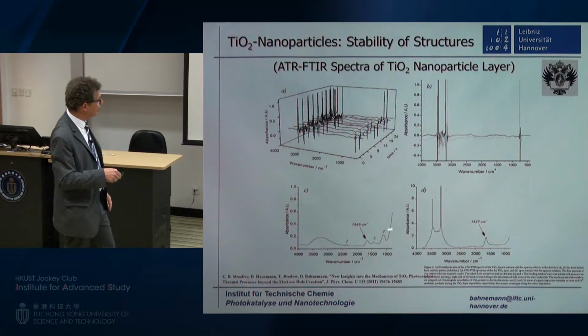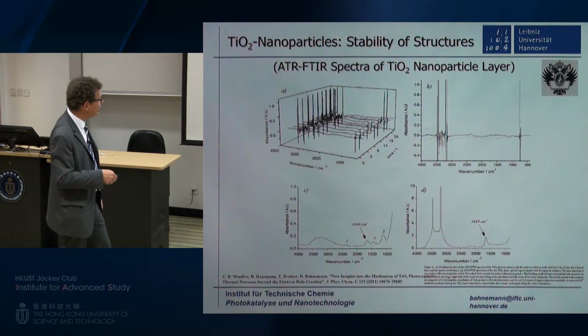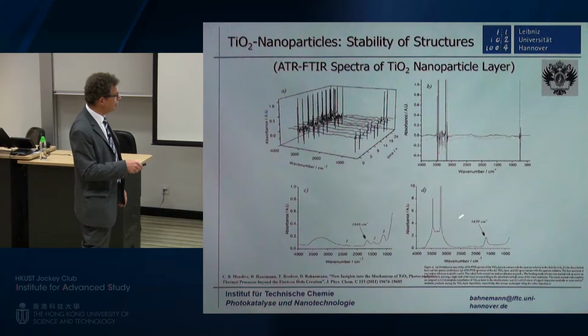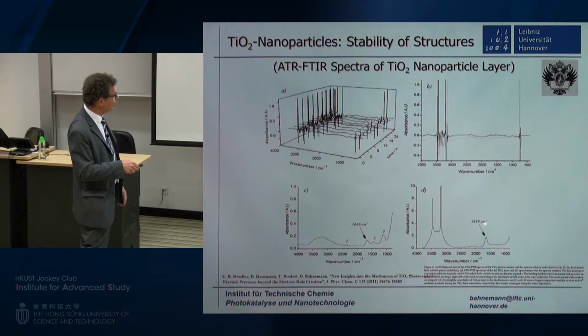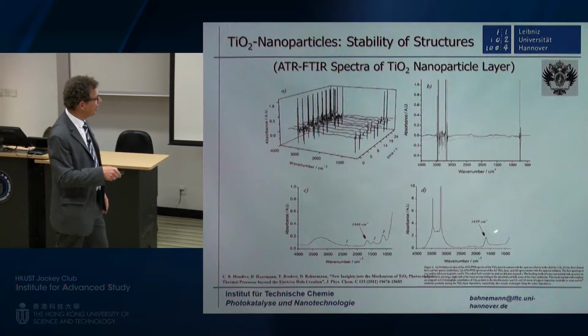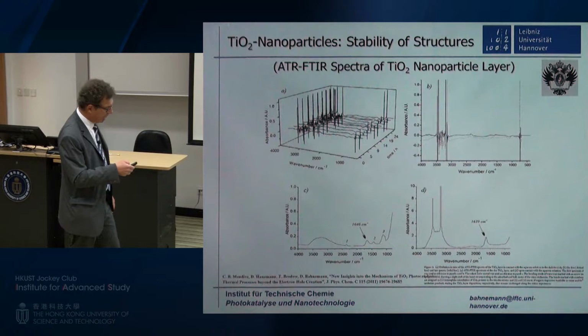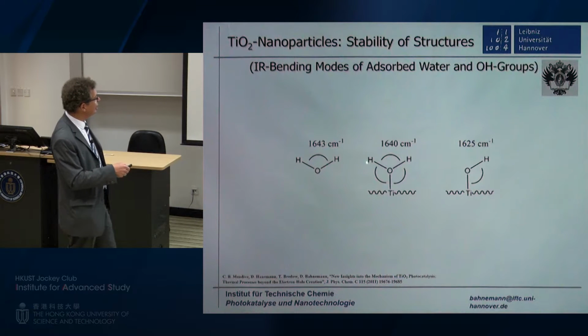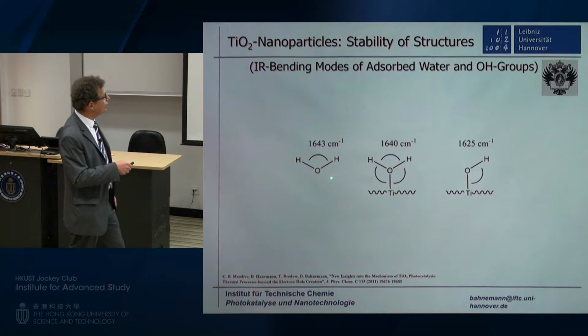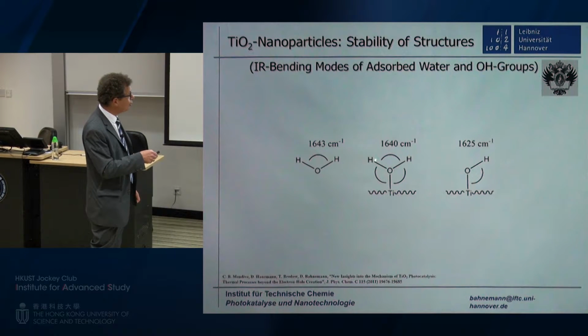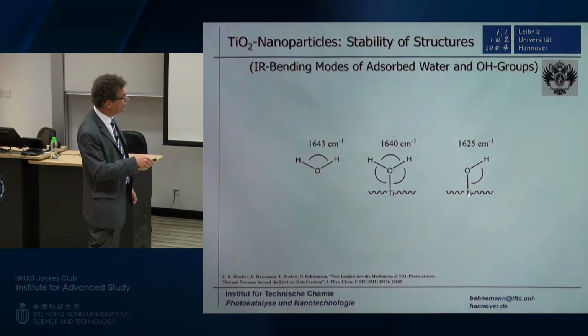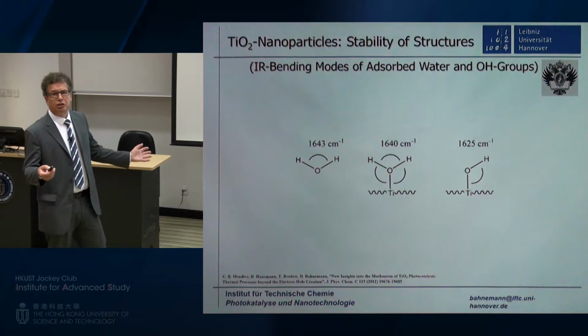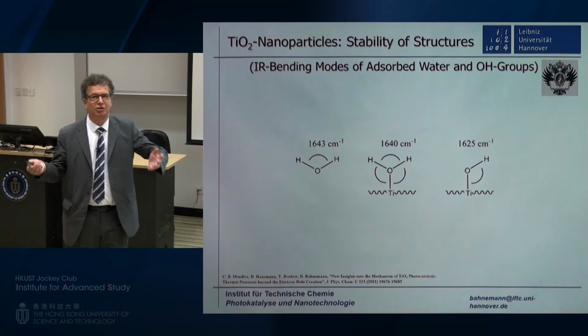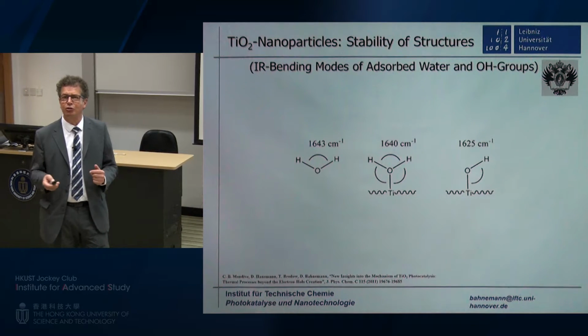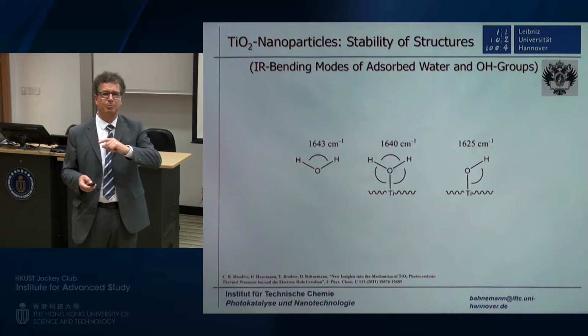You get certain bands here, and the interesting bands are around 1640 wave numbers. And if you look more closely, then you can see, oh, these are bands due to adsorbed water molecules, adsorbed hydroxyl. This is nothing new. This has been known in the literature for a long time, and we also see it. And now comes the blank experiment.